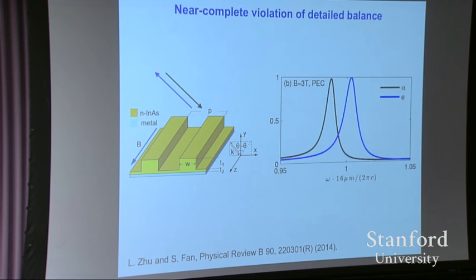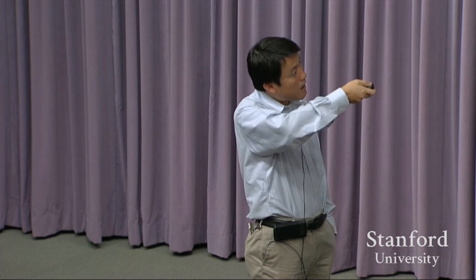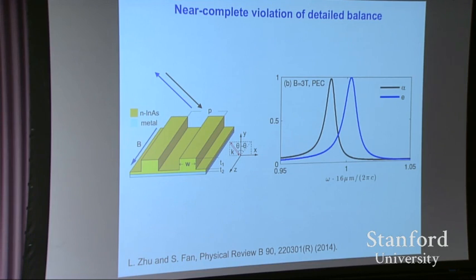And consequently, when you compute the absorptivity and emissivity of the structure, you will also see a split in the absorptivity and emissivity. So there are wavelengths where you have near unity contrast between absorptivity and emissivity in these structures. And that, we think, is an important initial step in trying to design something that breaks reciprocity in order to gain access to some of the thermodynamic potential that has not been available in most of the other structures.